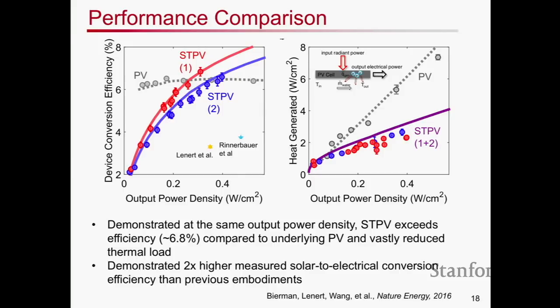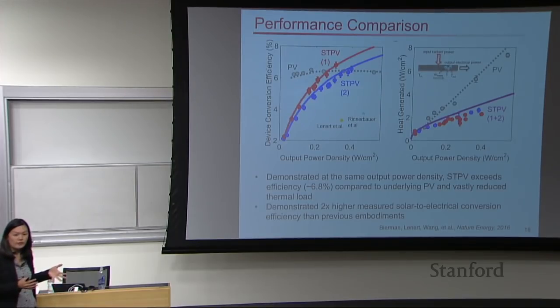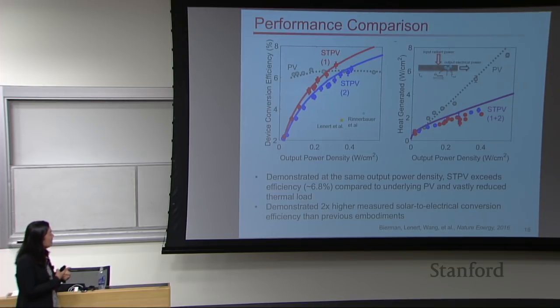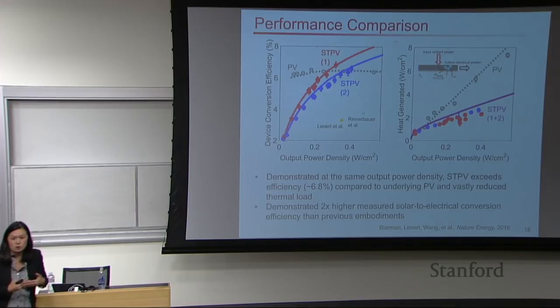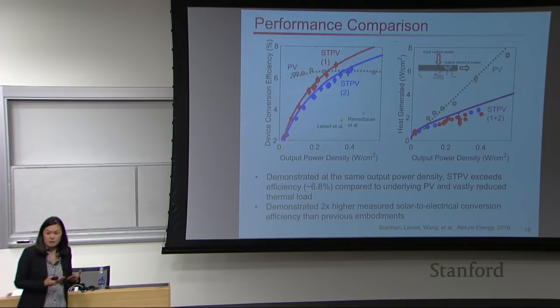So we were very excited about this result because what this shows for the first time is that, in fact, having this kind of spectral control using these nanophotonic selective absorber emitter structures, you can start to see that there is a spectral enhancement, right? So there's actually improvement because of this intermediate structure of the solar thermophotovoltaic. In addition, we were very excited about this result because, as expected, if you're able to use more effectively the photons that get converted to electricity, then thermal management should not be as much of an issue, right? A lot of the photons that were generating heat are no longer generating that heat because they're actually useful for the conversion process.